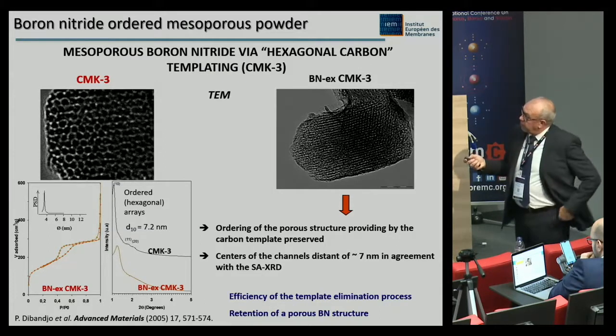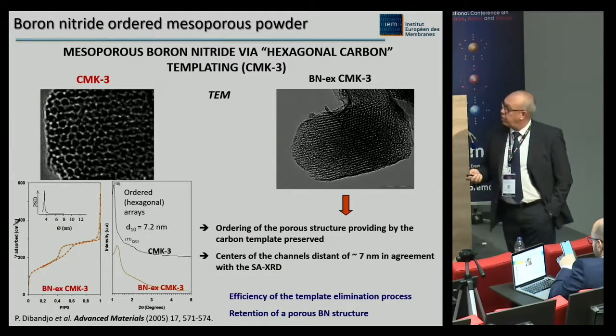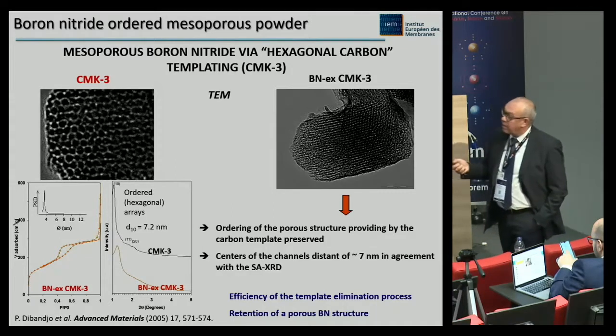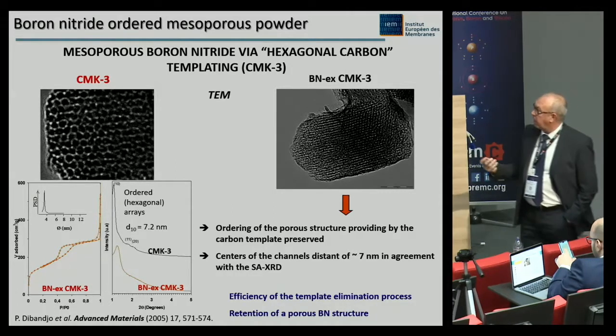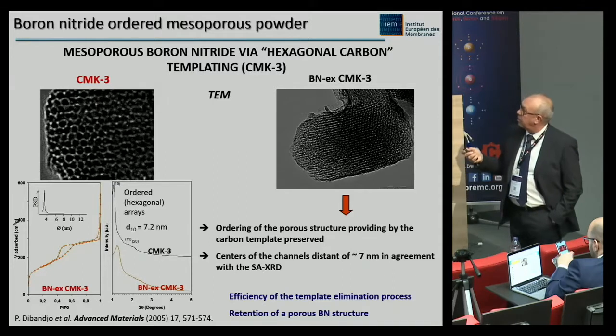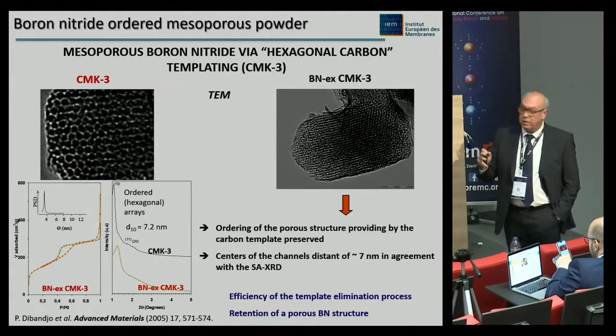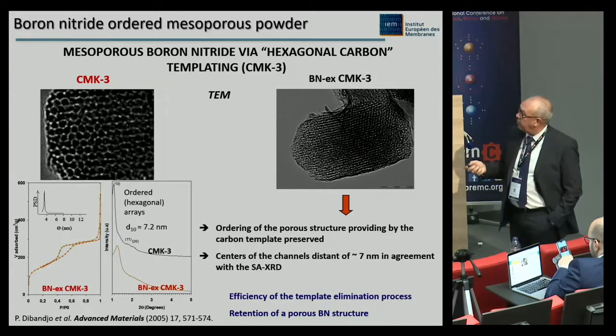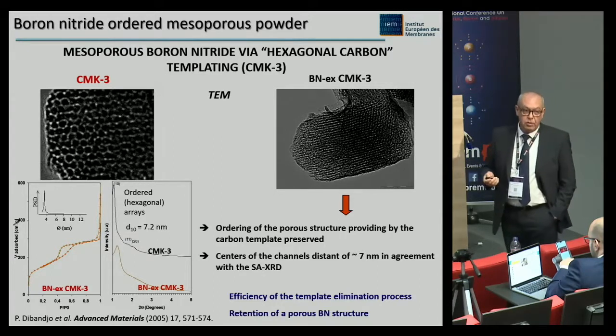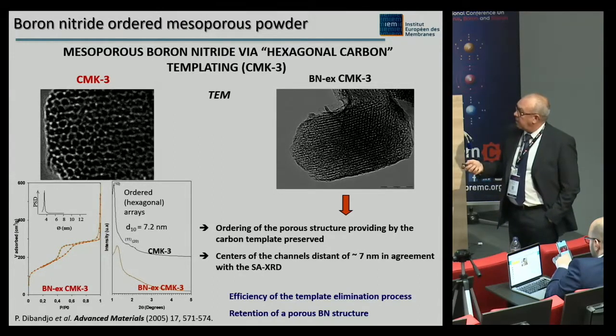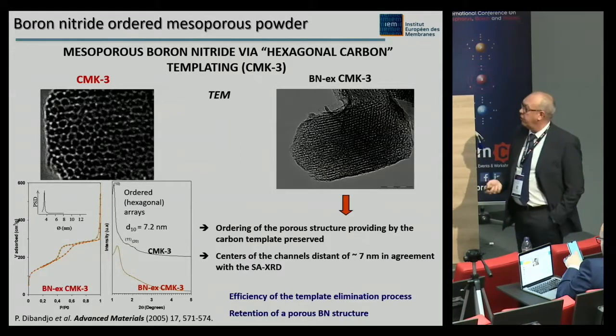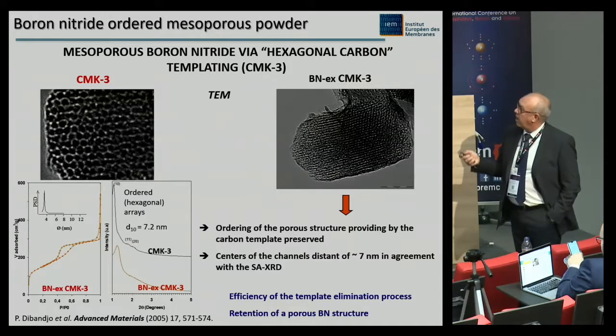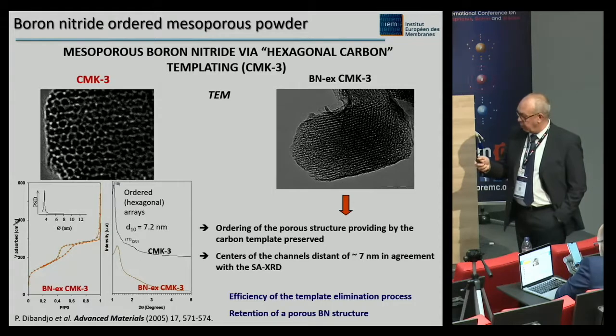So we have shown that the ordering of the porous structure provided by the carbon template is maintained. And you can see also that the centers of the channel are distant of about 7 nanometers, which is in agreement with the X-ray diffraction data. And that shows the efficiency of the template elimination process for the retention of porous structure.